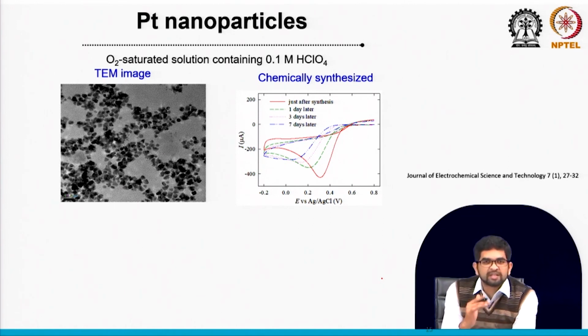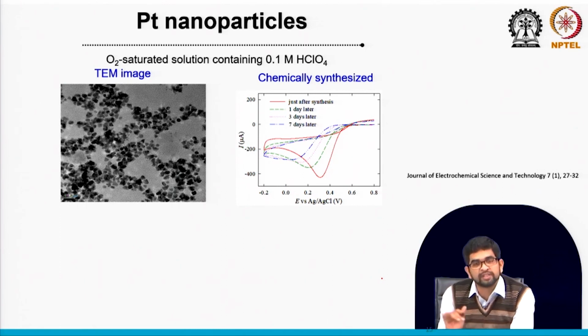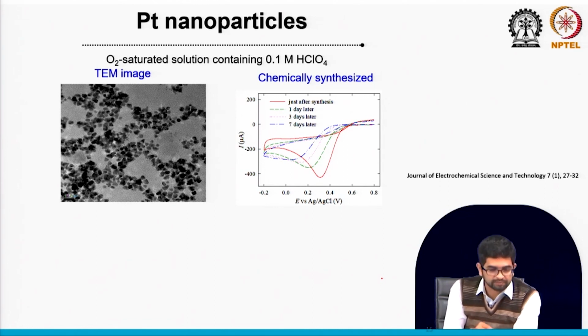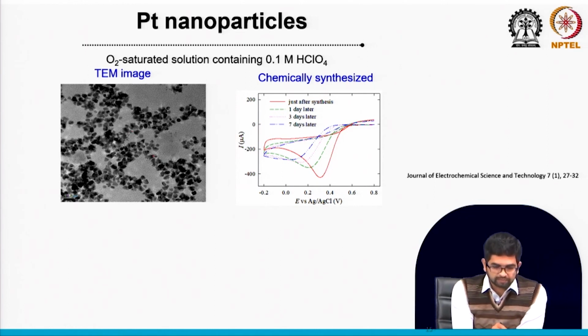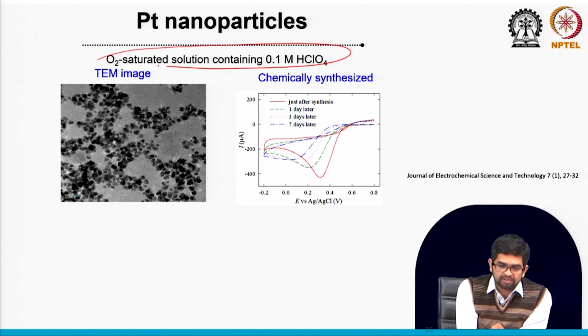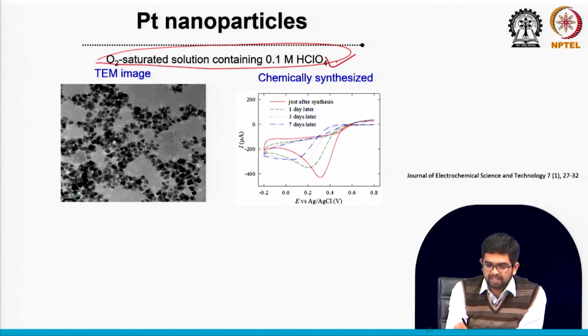But from here we can conclude on fundamental things: we should not store your nanomaterial or your disc electrode, or in general your transducer surface, for a longer time. But if you want to store, which condition you store in and how you modify the surface directly depends on how your electrocatalytic activity may change over time. Let us come to the nanoparticle. So here also we again checked the oxygen reduction reaction in the acidic medium.